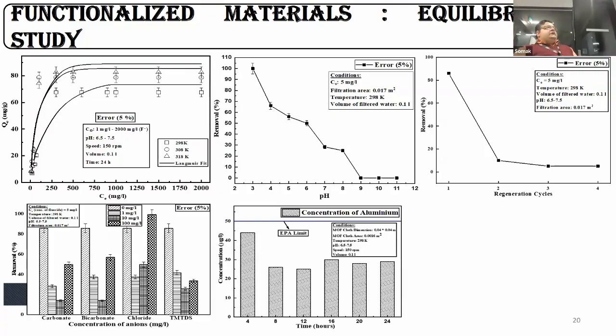We also carried out analysis for aluminium, another harmful metal ion. The EPA limit is around 40 to 50 microgram per liter. We found that over a period of 24 hours, there is leaching of aluminium taking place, but it is much lesser compared to the EPA limit.